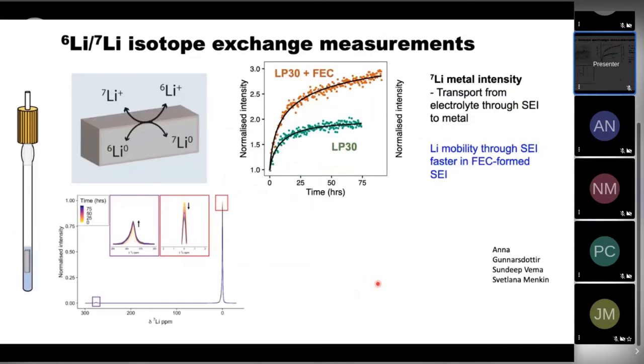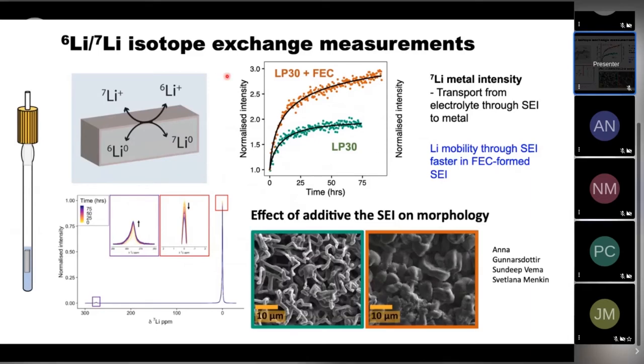And so what we've done to address this is to use different additives. And one of the most common additives is fluoroethylene carbonate, FEC. And then we measure the transport of lithium through the SEI by isotope exchange experiments. And these are very simple experiments where we put lithium metal, say we take lithium-6 metal and we put it in a lithium-7 electrolyte. And then we can quantify the exchange between the lithium-6 and the lithium-7. And what you're seeing in this measurement here is that transport through the SEI in FEC is much faster than in LP30, the standard electrolyte.